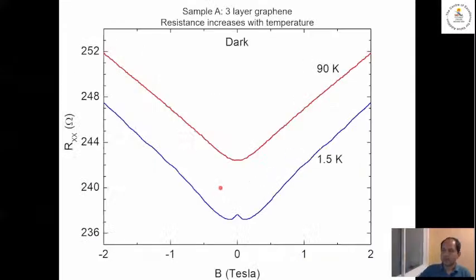So let's see what the results look like. This is with the sample in the dark, which means no microwaves. If you look at 1.5K, you get this blue curve going out to 2 Tesla. Then if you heat up the sample, the curve looks similar, it just moves up. So resistance increases with increasing temperature. This feature over here disappears.